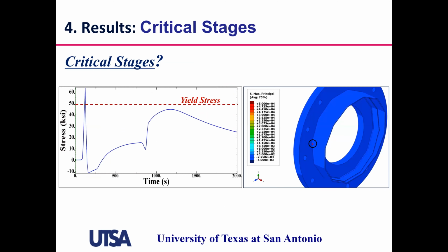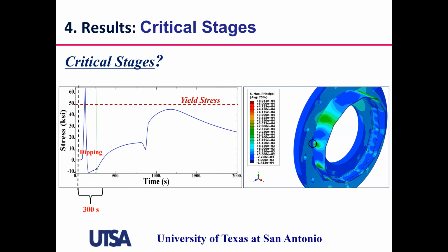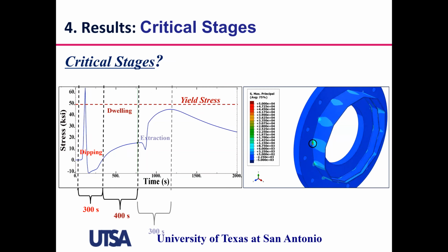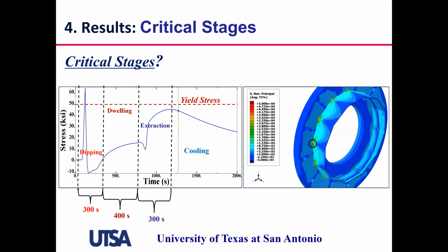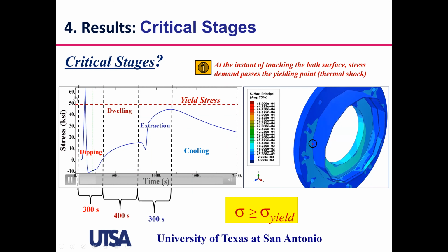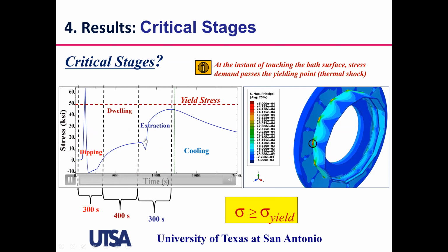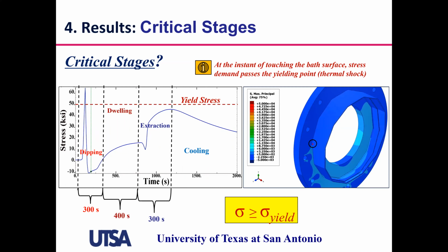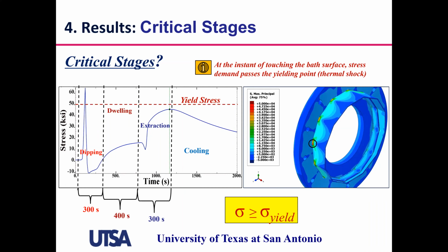And then let's look at what would be the critical stages of this galvanizing process. So here you'll see the stress results at a bend of the pole for the 4 different stages, which are dipping, dwelling, extraction, and cooling. So you can see during dipping, we have this huge thermal spike. And then during dwelling, the stresses somewhat level off. There's not much variation, but then during extraction, there's another increase in stresses, and then this levels off during cooling. But after this process, there are some residual stresses that are left on the structure. It is important to note that we use thermomechanical properties, and the mechanical properties are temperature dependent. So the yield stress is lower and changes with the temperature.